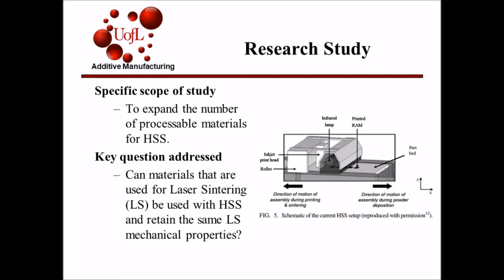The key question addressed in this journal is, can materials that are used for laser sintering also be used with high-speed sintering and retain the same laser sintering mechanical properties? Laser sintering is similar to high-speed sintering in that both processes require a powder that is able to flow at elevated temperatures. The amount of known material for high-speed sintering is limited, whereas nylon 12 is the standard feedstock material for this process. This journal tests two other common laser sintering feedstocks on the high-speed sintering and compares the mechanical properties.